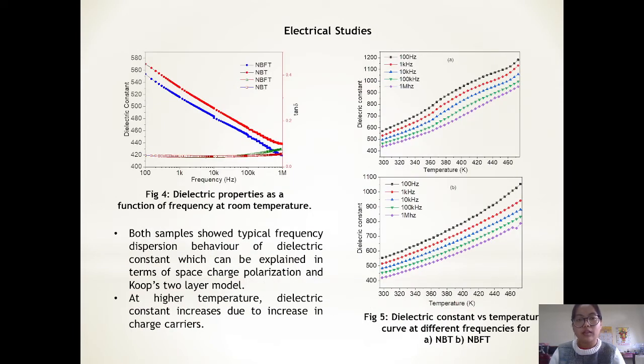The electrical studies were performed, and Figure 4 shows the dielectric properties as a function of frequency at room temperature. We can see that both samples show the typical frequency dispersion behavior, which can be explained in terms of the space-charge polarization and Koop's two-layer model.